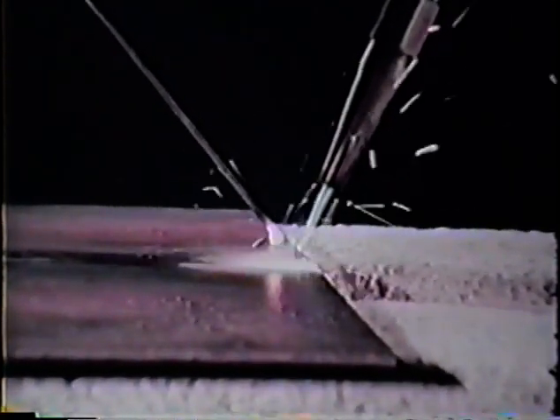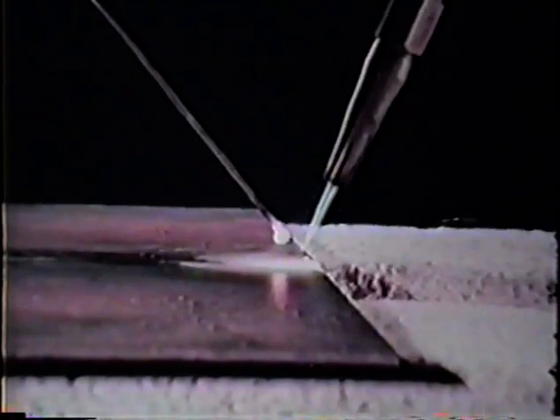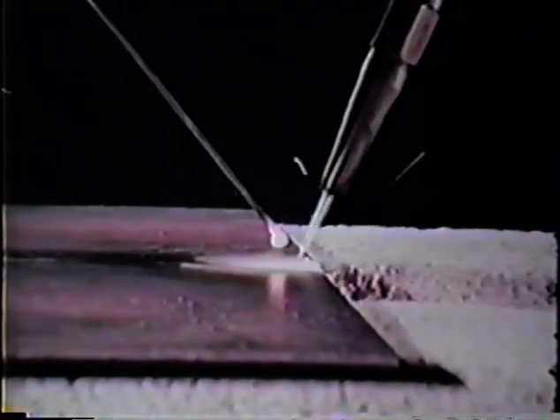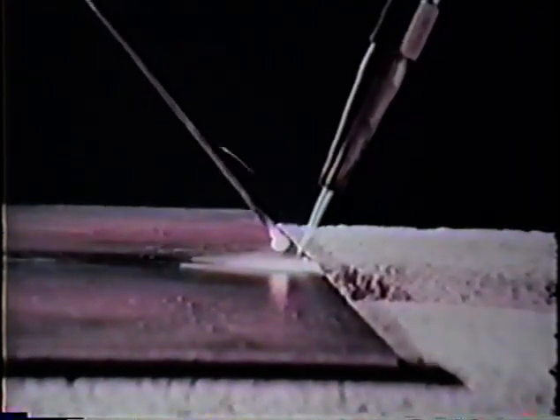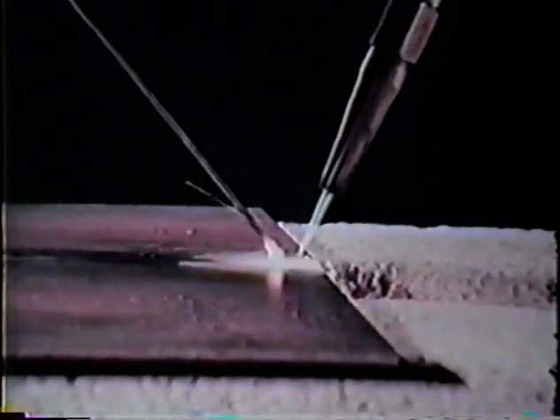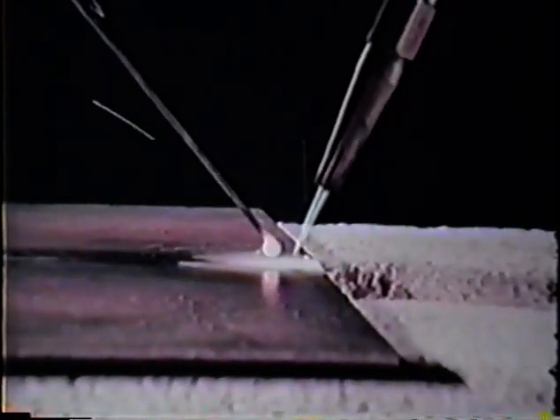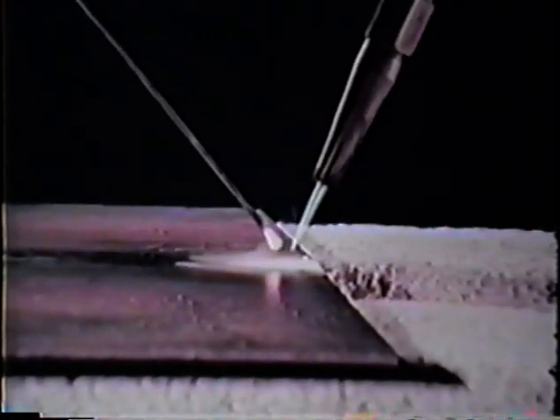Angle your torch to about 45 to 60 degrees to the plate and point it in the direction of the weld. The angle of the torch will depend on the needs of the puddle. The greater the angle of the torch, the hotter the puddle. Keep the inner flame cone 1/4 to 3/8 inch from the puddle.